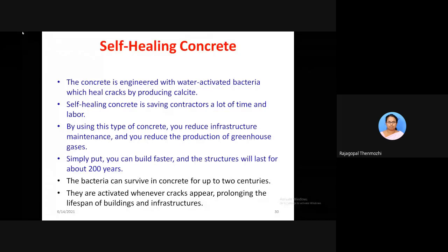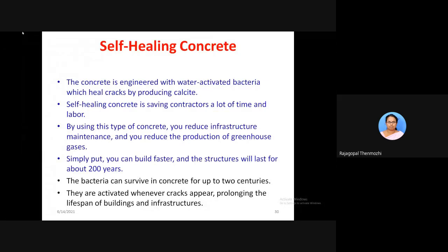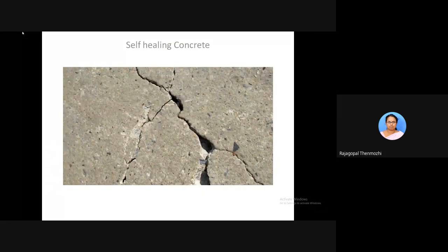So they are activated whenever the cracks appear, prolonging the lifespan of infrastructure. This is the way self-healing concrete works. These kinds of cracks we do not want to see, right? Once it opens, it just triggers. Up to this kind of width, we need not permit. If it just starts to show a micro crack, this bacteria will open up and excrete the calcite, so it will automatically close. That will be the job of the self-healing concrete if you are using it.